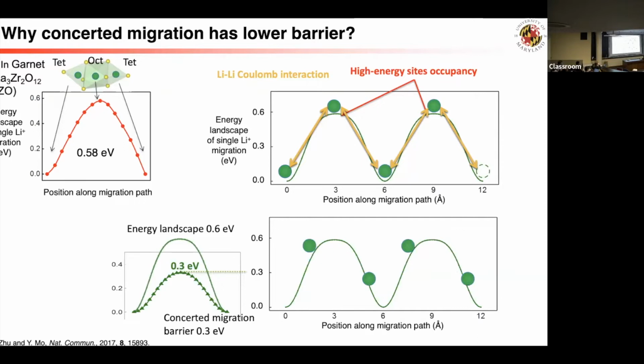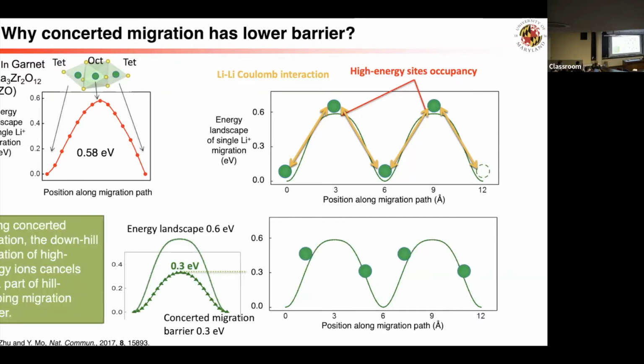If you can see the animation, it's probably much easier to see why that is the case. This is probably too small, but when these ions are climbing the hill, overcoming the 0.6 barrier, the ions at the top are moving down at the same time. So these ions going down cancel the barrier you need to climb, paid by the other atoms. As a result, you have more ions moving, but the barrier is actually lower. So that's how we understand why this concerted migration mechanism in lithium conductors produces such a low barrier: because of this high energy site occupancy, which has a canceling effect on the energy barrier.